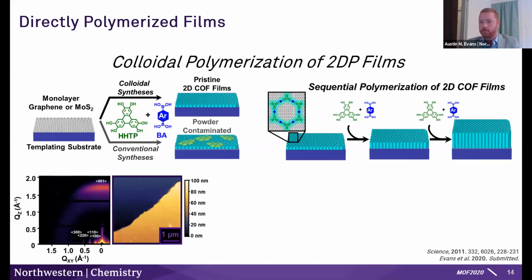Quickly, I'll just show you some data that these films are very, very smooth and have a very well-defined thickness. You can also tell, based on the grazing incidence diffraction pattern here and the concentrated intensities along the different axes, that these are well-oriented films, so they are lying normal to the surface. Essentially they've conformally coated the graphene layer that sits underneath them.